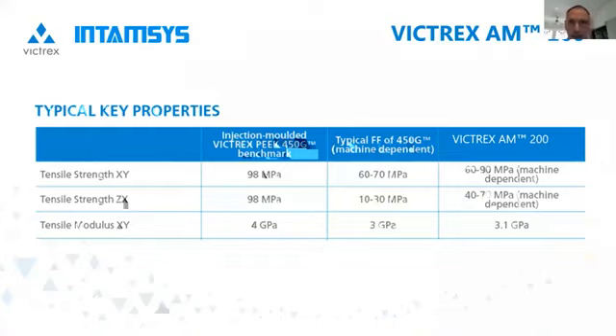And then in the last column on the right, you see some typical properties obtained for AM200 derived from machines, again, from across the industry. And here you can see an XY in the range 60 to even 90 megapascals, which is really like injection molded. And for Z direction of 40 to 70 megapascal. So with regard to properties obtainable from printing, again, it really depends on the machine and the profiles and how these are tuned.